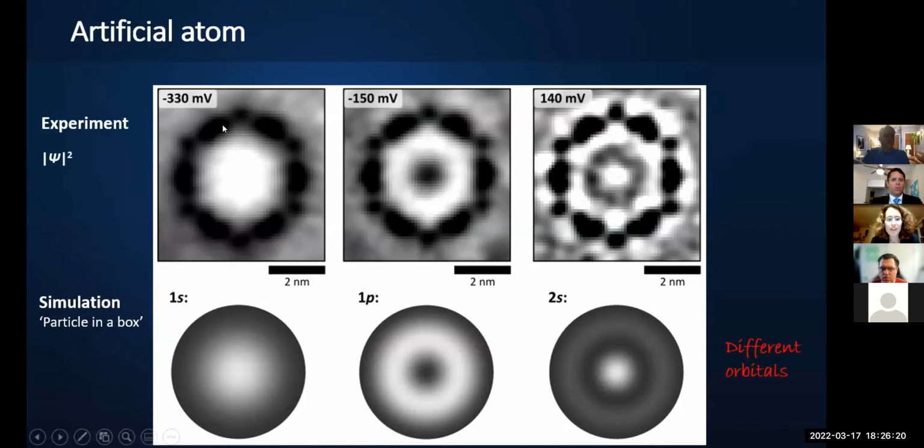And some of it will land on that cold surface, and because it's cold, it will stick. And that means we will have molecules basically scattered around on the surface, and we use our STM tip as a kind of broom to create these shapes. So it's like dusting it with a handful of sand, and then you're using the electron microscope as your finger to draw patterns in it. Basically, yes. Wonderful. Yeah, a very sharp finger, and that means that we can actually do it.